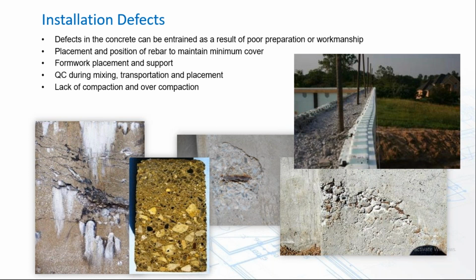Through overcompaction, we can see a separation of the larger and the small aggregates, as you see there in the middle, which results in an uneven stiffness or strength across that cross section. A lack of cover, as I mentioned, with the positioning of formwork, really leaves the rebar exposed at the very near the surface. Under compaction, we can end up with honeycombing, bug holes, and things like that.